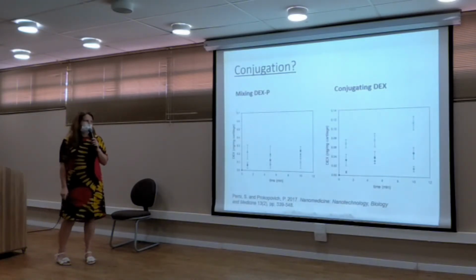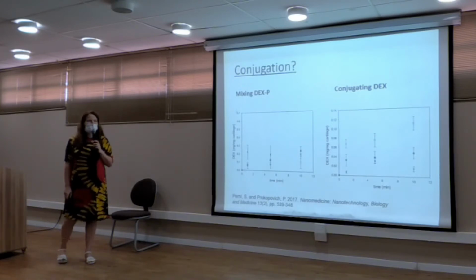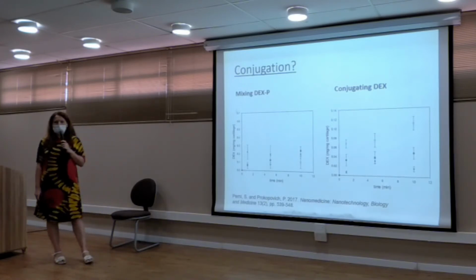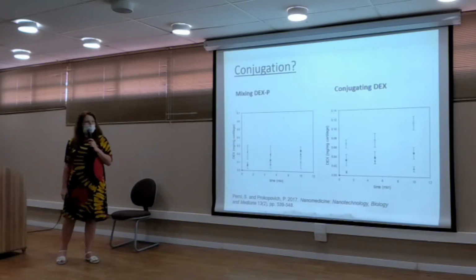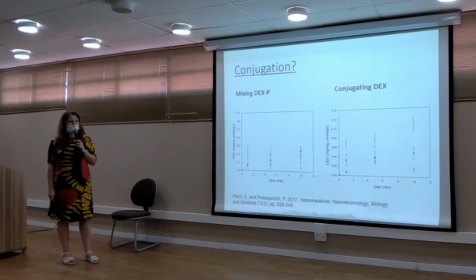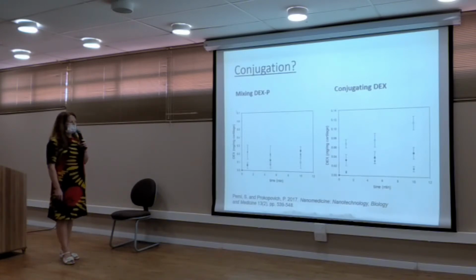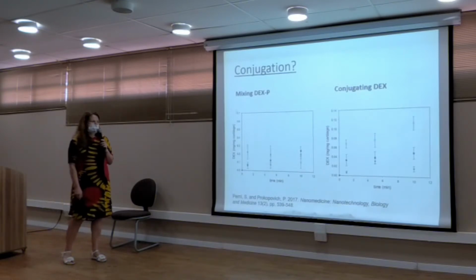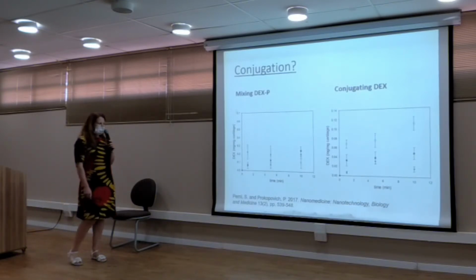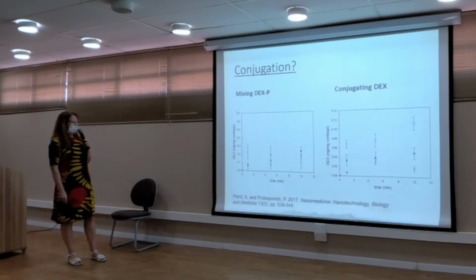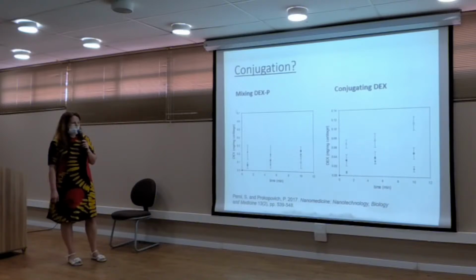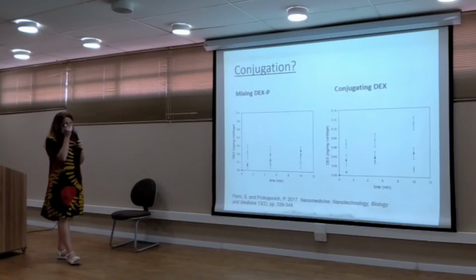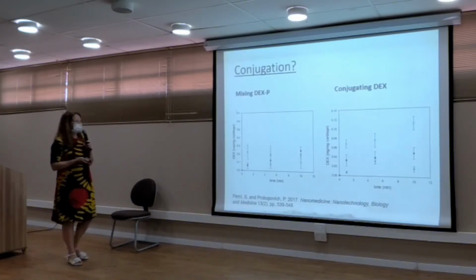Also, we questioned whether conjugation by itself is important, or whether we can do a self-assembly of dexamethasone with our polymers and get the same results. And the result shows that it is important. Conjugation is really critical for the system, because if you do not have a conjugation, your self-assembly is not as effective as the structures conjugated with the polymers.